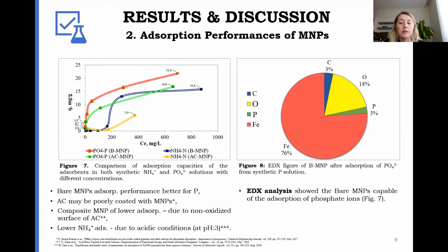And moreover, another reason could be ascribed to the employment of non-oxidized surface of activated carbon. During the synthesis procedure, we couldn't modify the activated carbon surface by any agent, so that it may have not helped the favorable surface functional groups to be produced in activated carbon. And lastly, we had comparatively lower amounts of adsorbed ammonium ions on both bare and composite magnetic nanoparticles. This is maybe due to the acidic conditions which were conducted at pH 3.